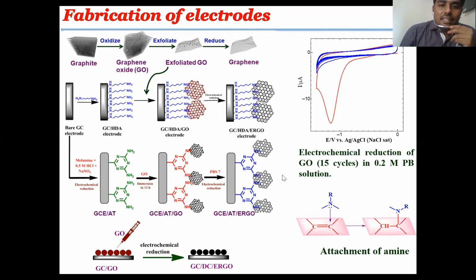How to fabricate the carbonaceous material on the electrode surface? The first case is graphene. Graphene, as we know, is synthesized from graphene oxide, which is synthesized from graphite. Initially, we have to fabricate the graphene oxide by self-assembly method with the help of the linker hexadiamine, and the graphene oxide is assembled on the surface of the hexadiamine amine functional group in the form of electrostatic attraction or nucleophilic addition, and the resultant electrode is employed for electrochemical reduction, which results in the formation of electrochemically reduced graphene oxide on the surface of electrode. The electrochemically reduced graphene oxide is nothing but graphene.